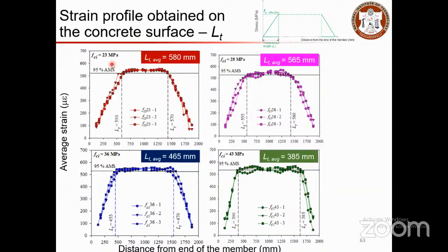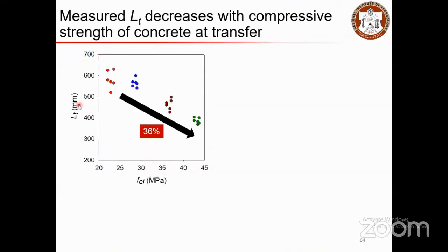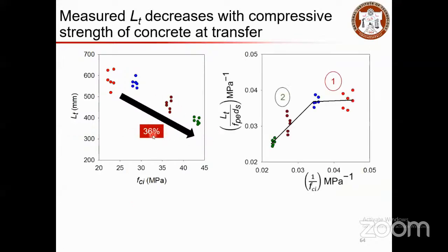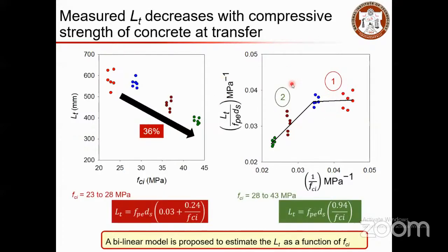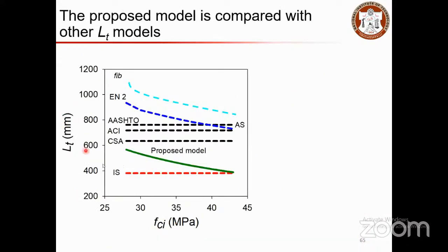From the obtained results, you can see the 95% average maximum strain method is used to get the transmission length for various strengths of concrete. It is summarized in this plot. This indicates that when you increase the compressive strength, the transmission length gradually decreases. From 23 to 45 MPa of strength at the time of release, the reduction in transmission length is about 36%. Likewise, the effect of stress is also induced. And from this result, a bilinear model is proposed to enhance the determination of transmission length. Similarly, based on the model, this was compared with the other standards as well.